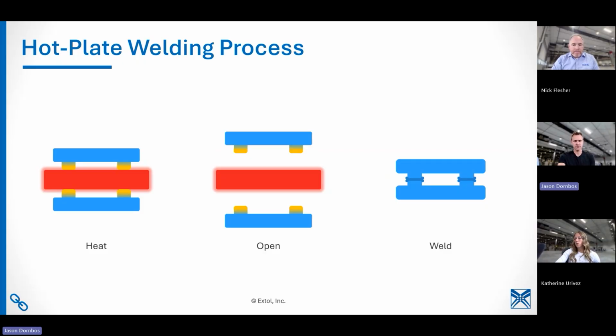Did we answer Steve's question about how the strength of plastic welds compares to parent material? In short, it does. Parent material strength is the industry term, and what that essentially means is if you have a given wall thickness and surface area, how much reduction do you get from the welding? If you're not familiar with that term, that's what that means. Really good welds are 90%.